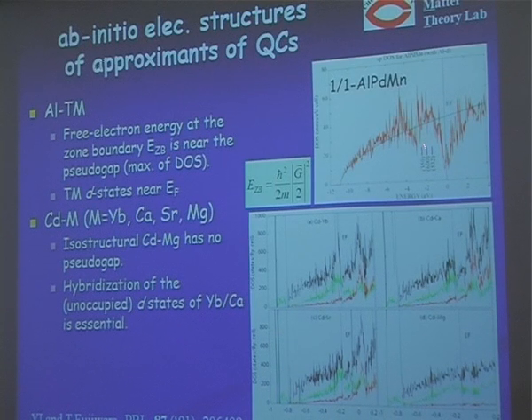And actually, the strong Bragg scattering, which gives the pseudo Brillouin zone, the energy for the zone boundary wave vector comes around here. So it is located at the peak of the density of states.